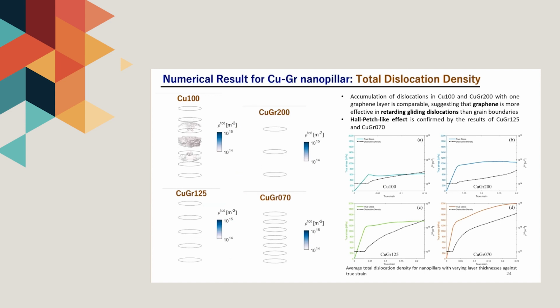The top left in this case corresponds to copper polycrystal, and the others are copper graphene composite systems: copper graphene, copper graphene, copper graphene. The range of total dislocation density is from 10 to 14 to 10 to 15.